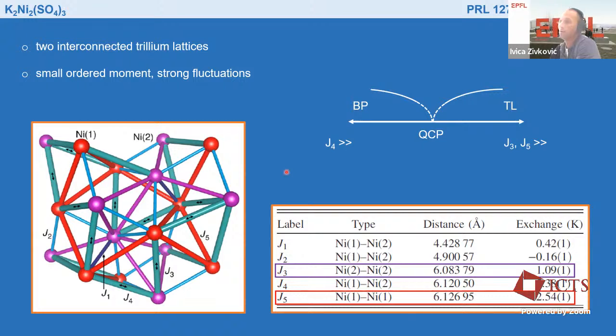On the other hand, if you set everything else to 0 and you have only J3 and J5, basically you will have 2 trillium lattices, which are not connected. So you could look at it from the point of view of a single trillium lattice. And as we have shown, in principle, there you can also expect a long range order. So that means that in one scenario, this compound could be sitting quite close to this quantum critical point just by accident, right?